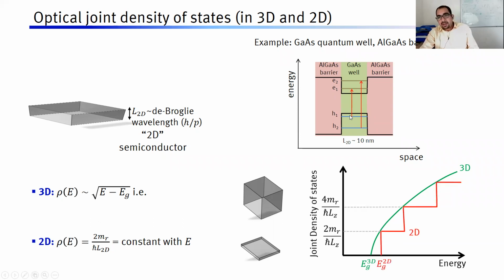So what happens is that when you hit this first transition, you suddenly have a step in the density of states. And when you have the second transition, you have another step. So the density of states becomes double. The amount of states available for the photons to interact with per unit volume of the crystal gets doubled. So this is the difference between the joint density of states for a 2D material, compared to a 3D material.